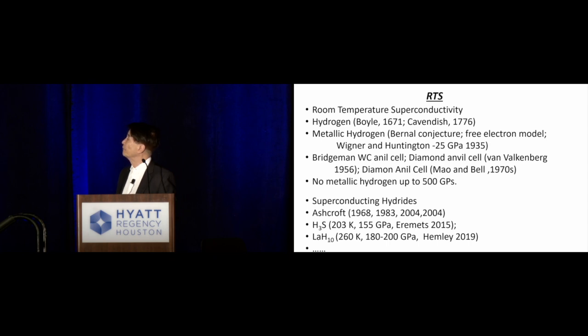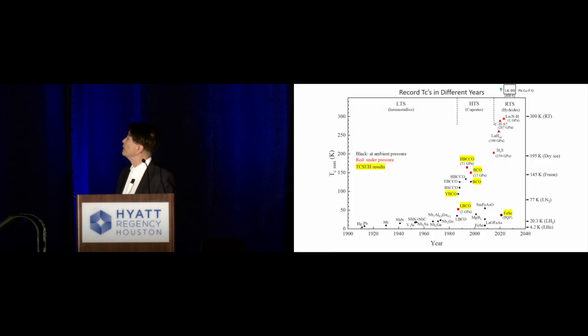And then immediately after that, in 2019, Hemley and co-workers at the Geophysical Lab, and later at the University of Illinois at Chicago campus, announced they found a compound, lanthanum hydrogen-10, superconducting with a transition temperature of 260 K when the pressure goes up to between 180 and 200 GPa. And so this goes on, and lots of claims of superconductivity near room temperature followed.